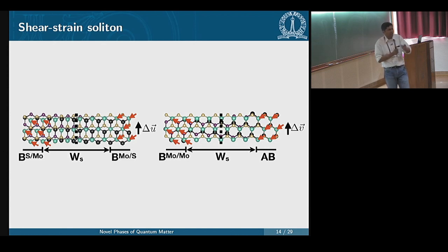If you take the difference, it points along the direction of the line, and these are nothing but what are known as strain solitons. They're solitons because if you do a finite temperature calculation, you will find that these things move together. They're always linked to the same dots. None of this topology will actually change.